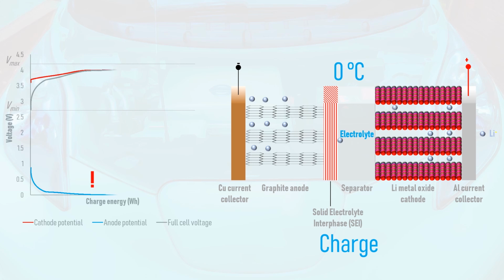Instead, they plate onto the surface of the anode, forming branch-like growths called dendrites, which puncture the separator between the two electrodes and form an internal short circuit, which rapidly discharges the cell, creates lots of heat, and can lead to the venting of flammable gases and even fire.